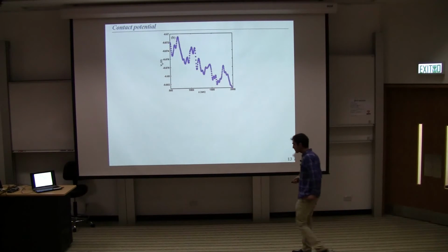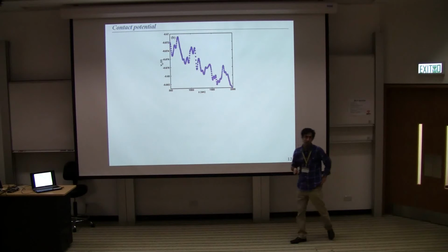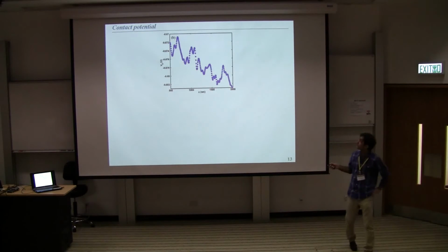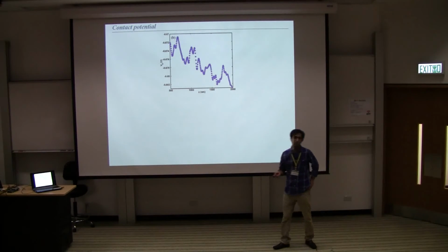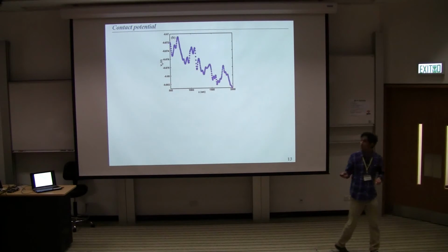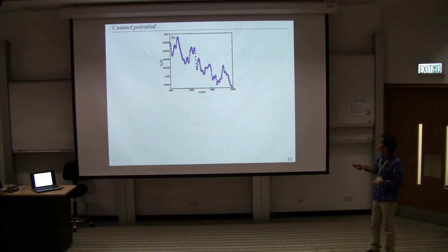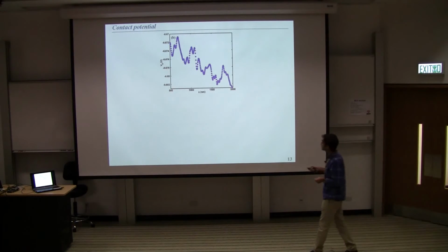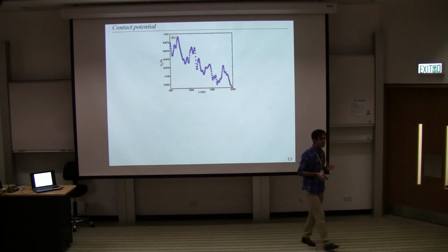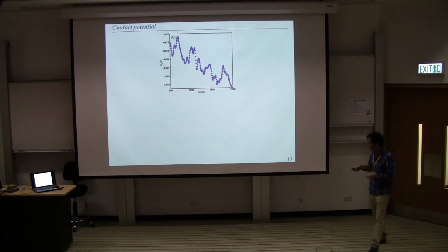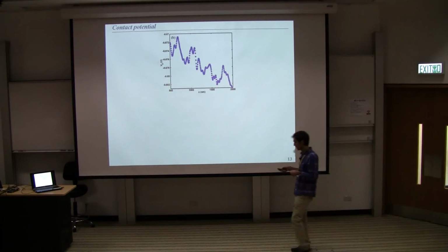Another important factor we extract from the data is the contact potential, because of the different work function of the sample. This high value for silicon carbide shows a significant contribution of patch potential to the total force and the origin of the deviation between theory and experiment.